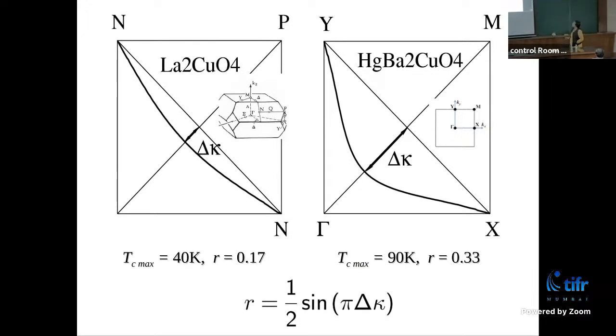The Fermi surface is pretty simple because you have only one band crossing the Fermi surface, and this one band is a copper oxygen antibonding band. Very simple. You can write the tight binding Hamiltonian, it's an undergraduate problem. But for lanthanum cuprate, you see the Fermi surface is more squarish compared to that of mercury. Mercury is much more rounded. If you define some delta K, how much it is bulging out, you can calculate something which we called the R parameter. This R parameter is 0.17 for the lanthanum compound, and for the mercury compound it is 0.33. TC 90 Kelvin, TC 40 Kelvin. So clearly there is something between these two.